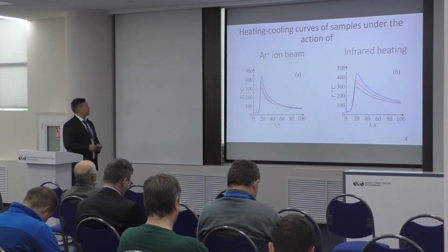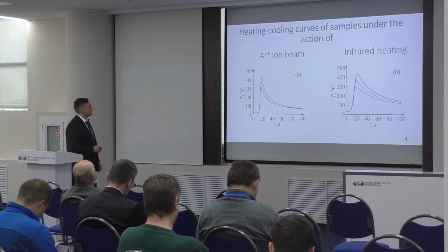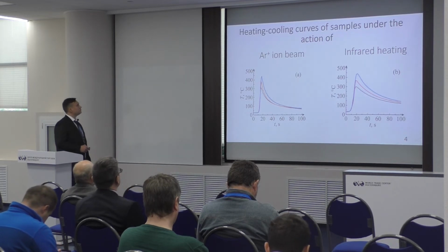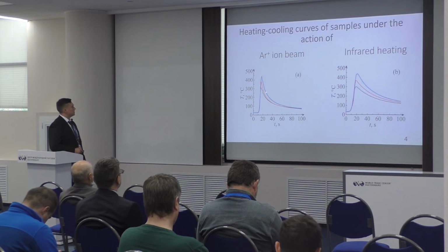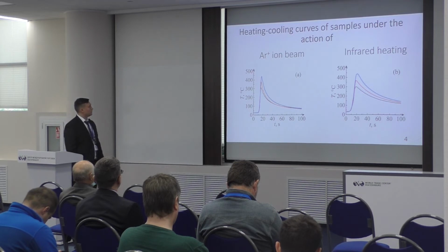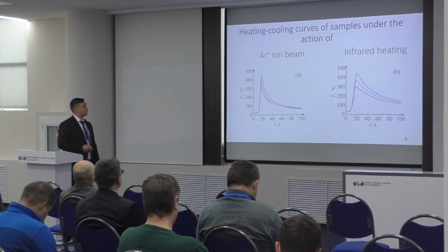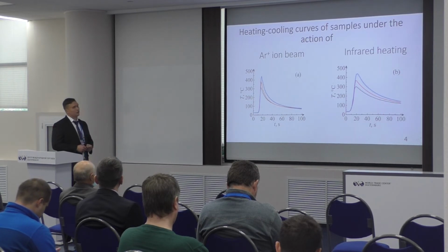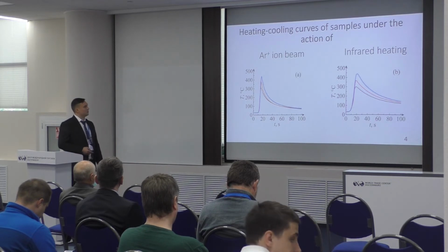On this slide you can see the heating and cooling curves of our specimens under the action of ion irradiation and infrared heating. Blue, red and black curves are different temperatures of impact. The infrared heater has the same power density as the ion beam.